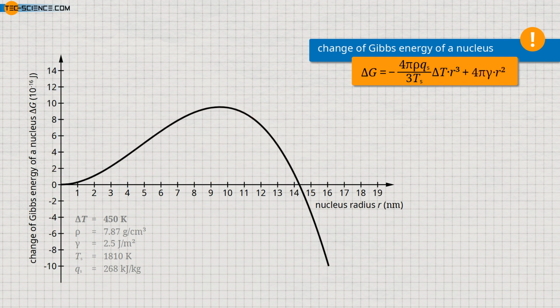First, we assume that a solid nucleus with radius r1, which lies to the left of the maximum of the Gibbs curve, is formed by chance. To form such a nucleus, the Gibbs energy must obviously be increased by a certain amount delta G. This is done by statistical fluctuations in the thermal energy of the melt, which can supply this amount of energy in the short term. If the nucleus is to grow further and thus initiate the solidification process, it must obviously become larger. According to the diagram, however, an increase of the radius is only possible with a further increase of the Gibbs energy. However, as already explained, such an increase in Gibbs energy does not spontaneously occur. Rather, the decrease of the Gibbs energy and thus the decrease of the size of the nucleus is more probable. The consequence is therefore that the formed nucleus dissolves again with the release of energy.